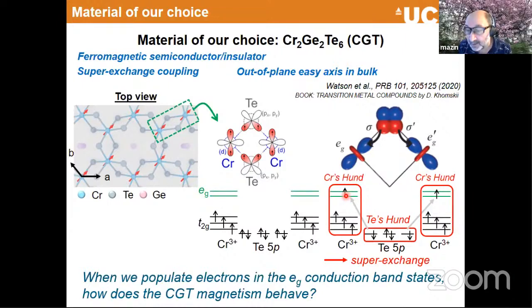And the other thing that comes to mind, because of the Mermin-Wagner theorem, maybe somehow you reduce fluctuations, but that's a logarithmic effect, and it should be very weak. So you really have to modify your exchange coupling to get this strong effect that you have so far. So the logarithmic effect, yes, there is that here as well. Okay. All right.